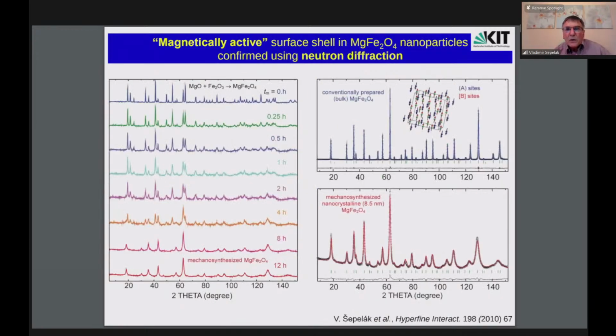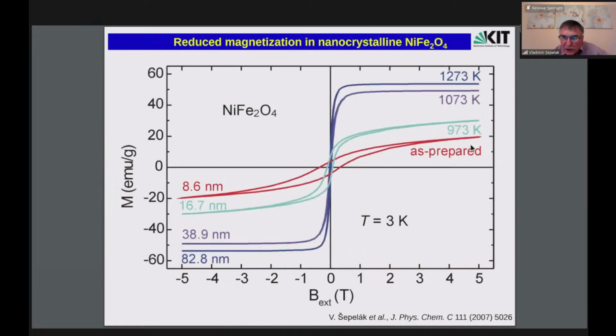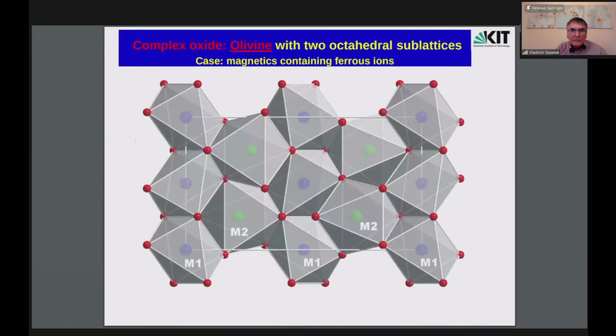In the case of nanocrystalline nickel ferrite, which was prepared by mechanosynthesis, we observed reduced magnetization. That means in this case, spin canting was the prevailing effect over the non-equilibrium cation distribution. And you see, if we heat this material, saturation magnetization increases, and after heating at this temperature, this magnetization is close to that of bulk material.